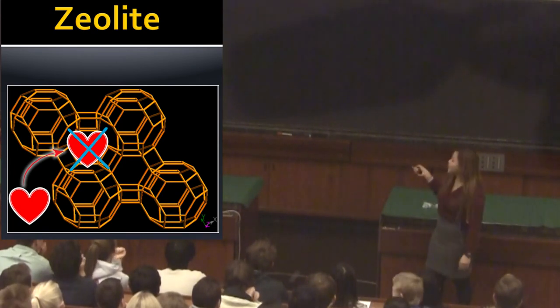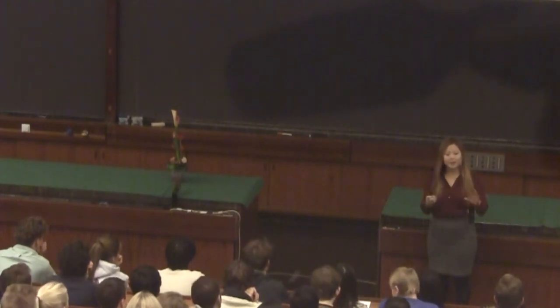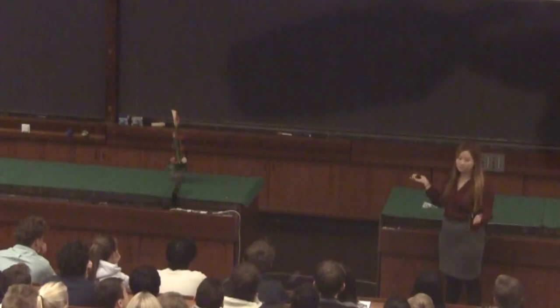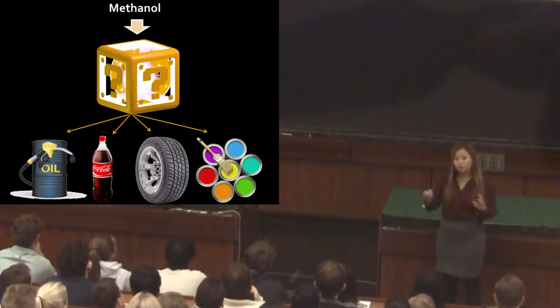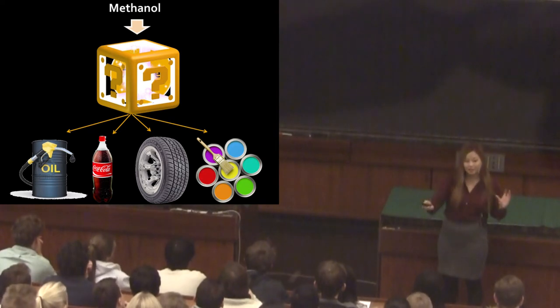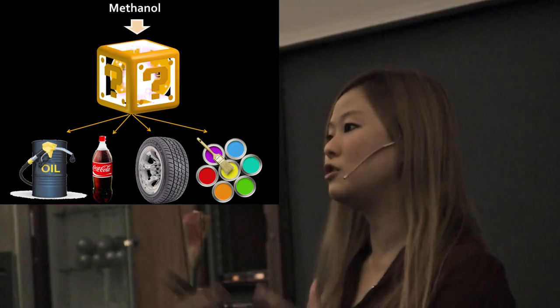So because all the channels are different in the different zeolites, it's like a boundary — you can come in, you can't come in. They decide which molecules can react. So from methanol with the zeolite, you can make hydrocarbons. And depending on which zeolite you use, because they differ in the size of the channels, you can make different products. It depends on which zeolite you use.